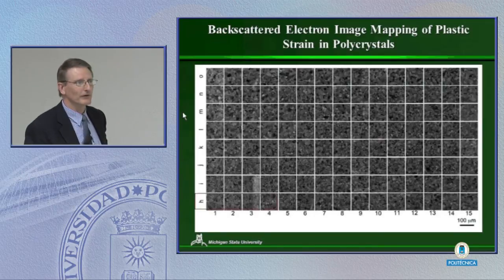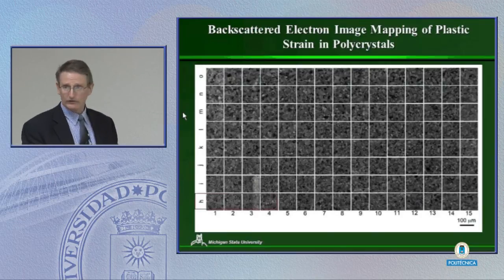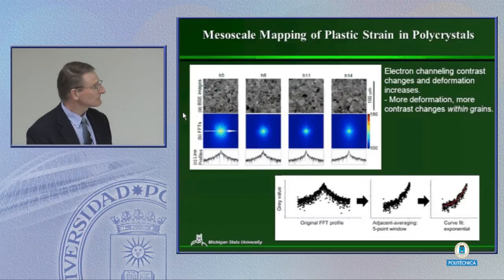And that's really simple to do. Just go in there, have an undergraduate snap image after image. But what happens is the images near the crack tip look different than the images far away. Because near the crack tip, there's more dislocations, there's more crystal rotations, and the channeling contrast is going to be different in those areas. So as a consequence, again, if you move far away, you can see the grain structure in these backscattered images fairly easily. But close to the crack tip, because of the crystal rotations, we get more channeling bands and things like that. It becomes harder to see those.